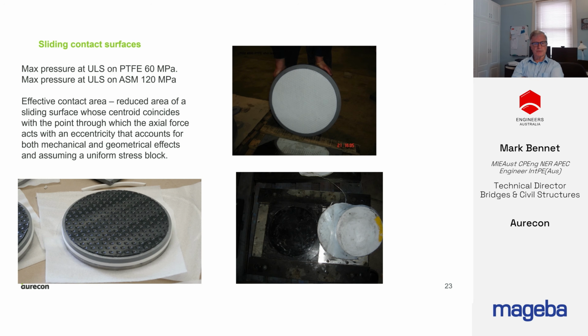Sliding contact surfaces. The maximum pressure allowed on PTFE at ULS is 60 MPa. There are new advanced sliding materials, typically ultra-high molecular weight polyethylene or fluoropolymers, that have a maximum pressure allowance of 120 MPa, but that limit is temperature dependent, and the pressure is calculated on an effective contact area. This photo shows an old style PTFE sliding surface. In the past, the PTFE wasn't dimpled. If the pressure is excessive, then the PTFE can extrude, or shavings of PTFE can get shaved off the Teflon disc.